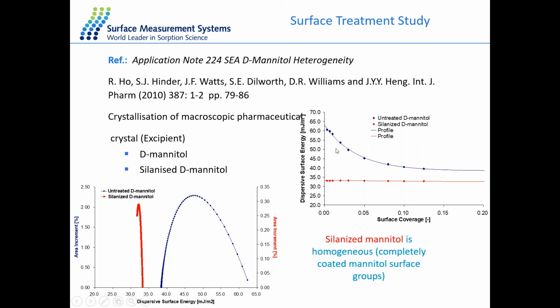We can also take a point-by-point integration of these points on this profile, and as a result, we will have the dispersive surface energy distribution. What this is telling us is that the wider our peak, the more heterogeneous our surface, and the more narrower our peak, the more homogeneous our surface.